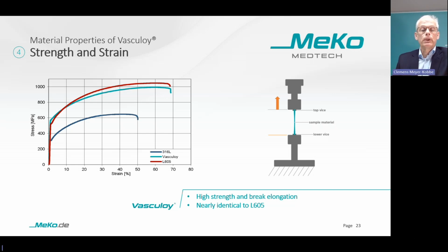Nowadays, L605 is a typical material for coronary stents. Nearly all coronary stents are made of L605. L605, here the red line, has a high strength of slightly above 1000 megapascal and a very high break elongation of nearly 70%. When we developed Vasculoy, we tried to mimic the mechanical properties of L605 as good as possible. Vasculoy has about the same strength like L605, only a bit less than 1000 megapascal. And the break elongation is the same.